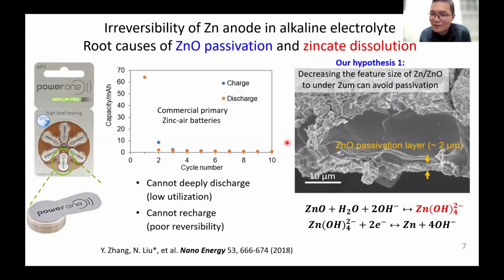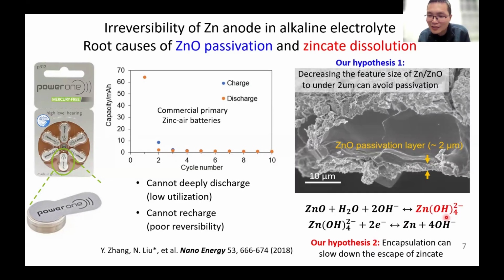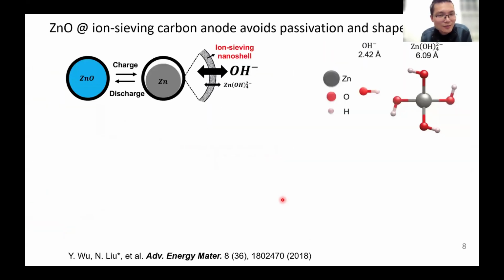We also have a hypothesis to address this problem. The hypothesis is to encapsulate zinc inside a confinement structure so you can slow down the escape of zincate. So with these two root causes and their hypotheses, we designed this kind of structure. This is a zinc oxide nanoparticle, so it's small in size, less than the critical passivation thickness. And outside we have a carbon coating, which will encapsulate the zincate species and slow down their dissolution. So we have two approaches in this design to address the two root causes.